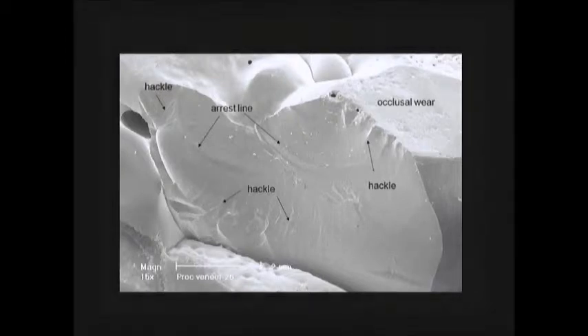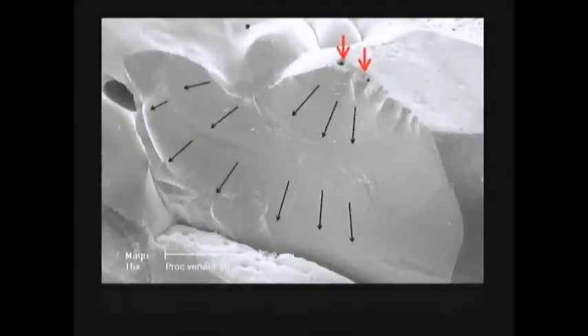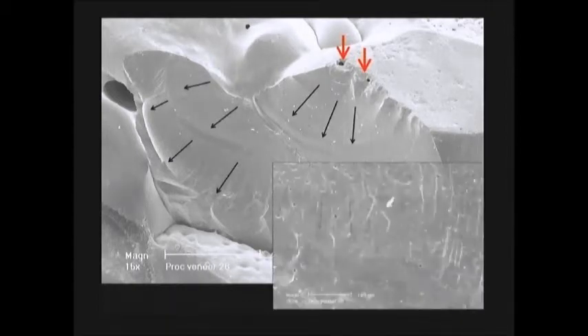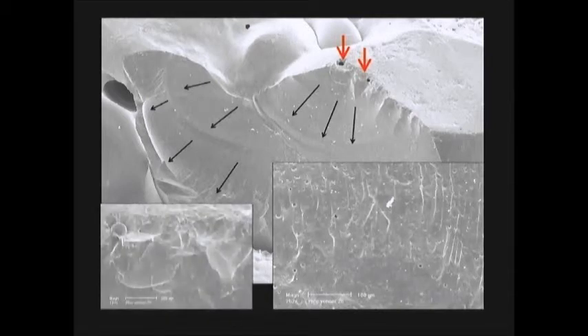Unfortunately with replicas, you also have artifacts, little bubbles. You have to just forget them. But if you try to figure out what is happening here on that occlusal surface from which the crack started, well, by the way, you can figure out, you have little wake hackle, lots of wake hackle here. So the replica shows you really a lot of information. Well, here we had 2 indents again. So you want to see indents, you can see them.